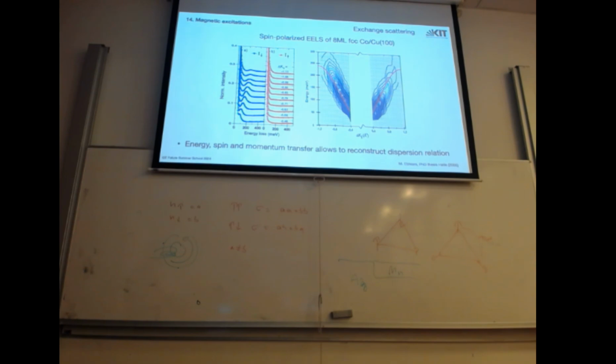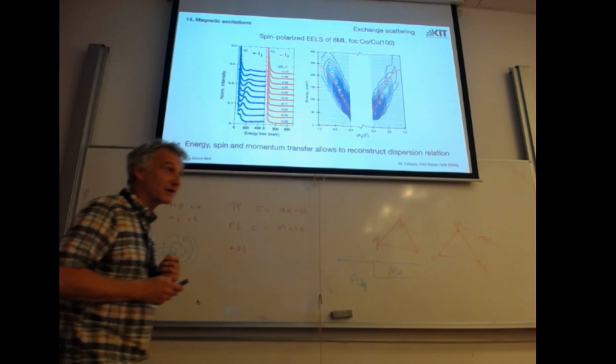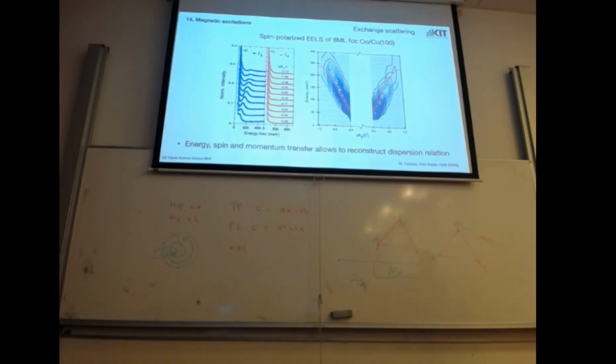This is at very low temperatures. So the inverse process, the annihilation of the magnon, is unlikely because there are no thermal magnons. So we don't see this feature in the other spectrum. So we know this excitation has one h-bar and is only reducing the magnetization. This is a magnon. How do we move in which direction this electron?